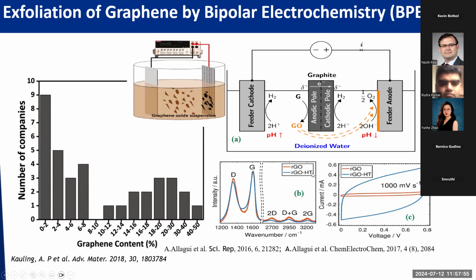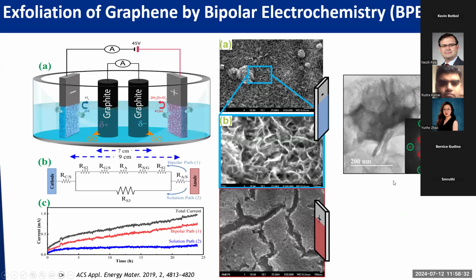And this graphene, when he did Raman and CV, he found is actually not that high quality. He has to use a high temperature to further reduce the graphene. You can see from the CV, without further high temperature treatment, the RGO, although he claims it's RGO, is not really highly reduced. It's like just graphene oxide, so he has to reduce it by a high temperature process. So we looked at this system, talked to students, and talked to Anis, and discussed how to further improve this. Basically my student modified the basic bipolar electrochemistry.